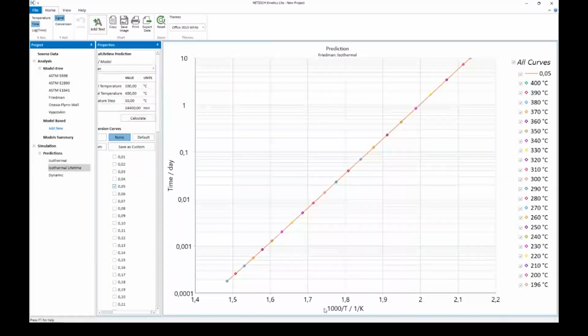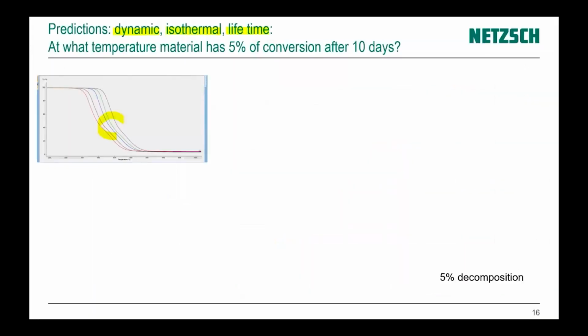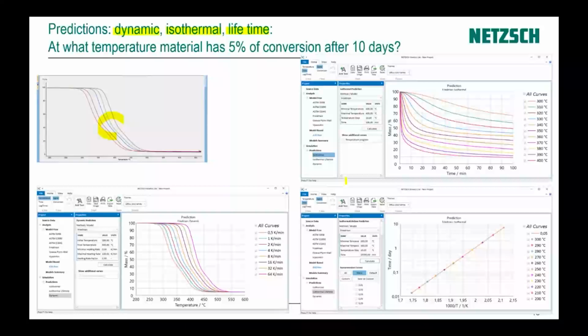Here we have the solution. Horizontally is 1000 divided by absolute temperature. Vertically is our time. We have maximum value of 10 days, and the last point shows us the temperature for 5% of conversion, where the material has 5% of conversion after 10 days, and this is the last curve. The last point, 196 degrees. So we have found the temperature at which material has 5% of conversion after 10 days. So it is relatively easy. Now we can go here. We have found everything, and it works nice.